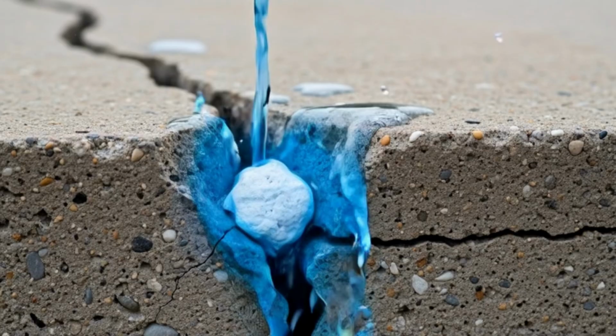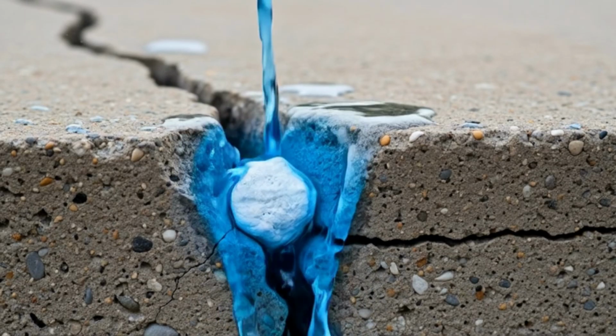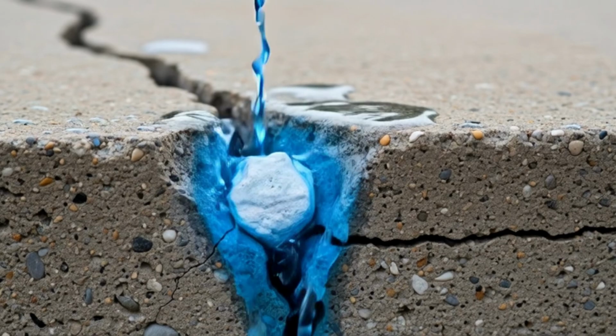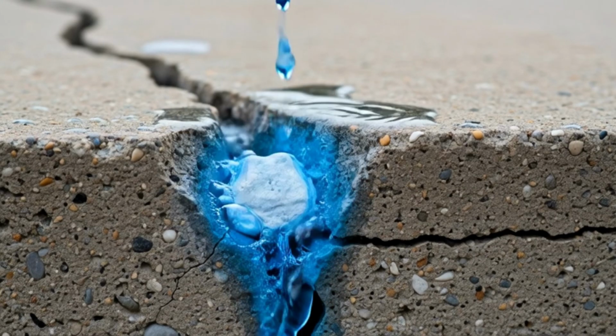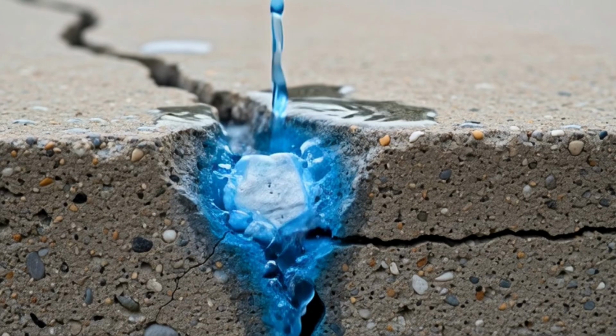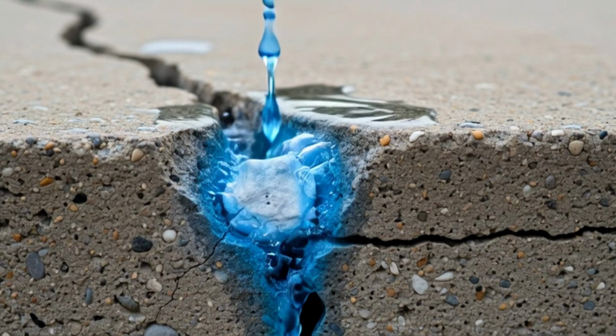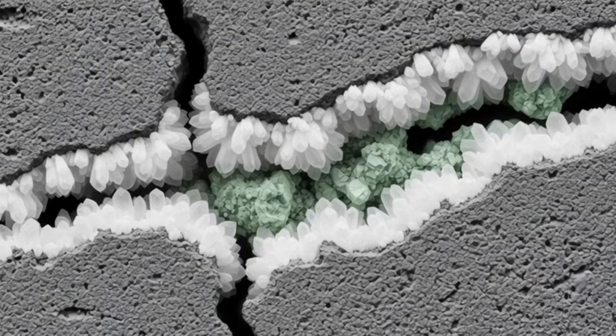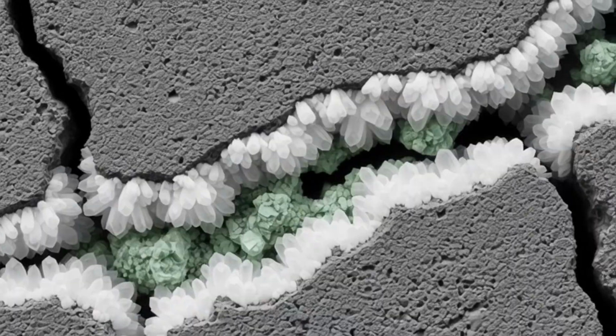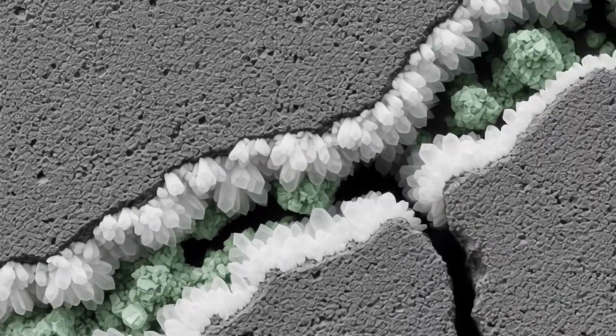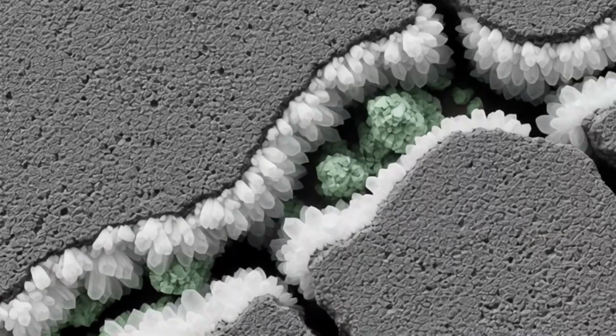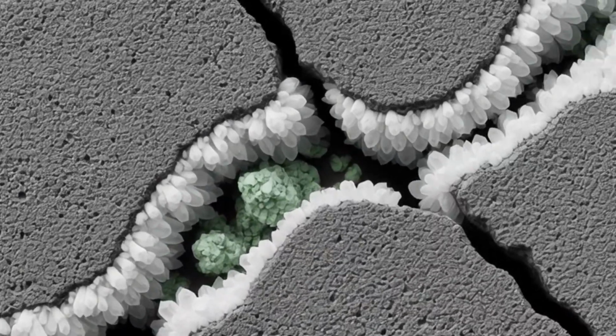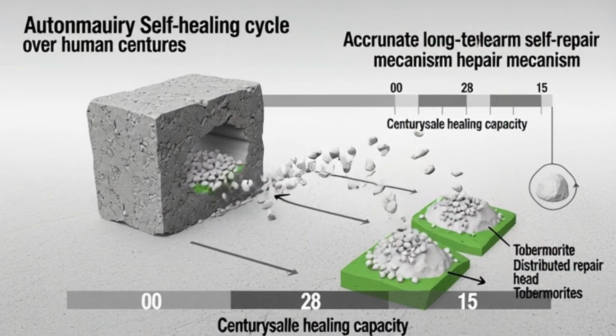The self-healing mechanism. Over time, the concrete cracks. It's inevitable: thermal expansion, settling, stress. Water enters the crack and reaches a lime clast. The quicklime reacts and forms calcium hydroxide. This calcium hydroxide is supersaturated and unstable. It precipitates as calcium carbonate, limestone. The calcium carbonate fills the crack, seals it, and prevents further water penetration. This is autonomous self-healing, with no human intervention. The material repairs itself. The reaction continues as long as unreacted lime clasts exist, potentially centuries.